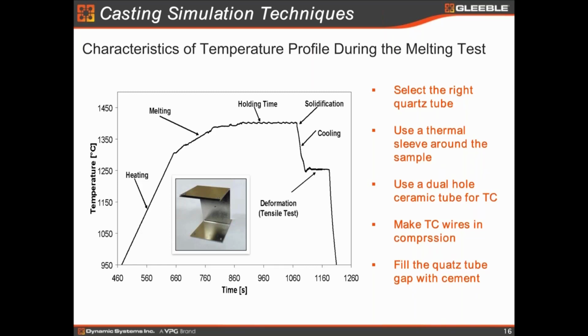So a rule of thumb is, if you know the thermal expansion coefficient of your steel, with the phase transformation, you try to estimate what the final diameter would be at the melting point that you will see. So the inside diameter of the quartz has to be a little bit bigger than that. Otherwise, you would break the quartz, because quartz is very brittle.